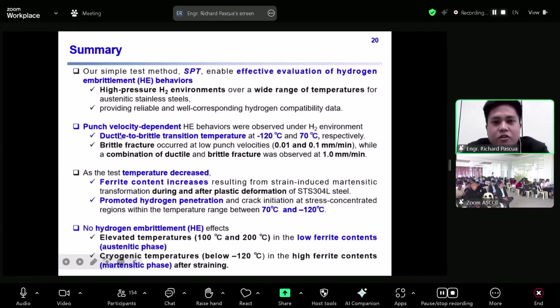As the summary, we confirm the effectiveness of our in situ SP test or SPT method in evaluating the hydrogen embrittlement behaviors of austenitic stainless steel at different temperature conditions, and it provides reliable and well-corresponding hydrogen compatibility data, which is comparable to the other research group. And we obtained the punch velocity dependent behaviors between negative 120 degrees Celsius and 70 degrees Celsius. And as we decrease the temperature, we observed that the ferrite contents of this material continuously increases, particularly from 70 degrees Celsius to negative 120 degrees Celsius, which promoted the severe hydrogen embrittlement effects in the material.